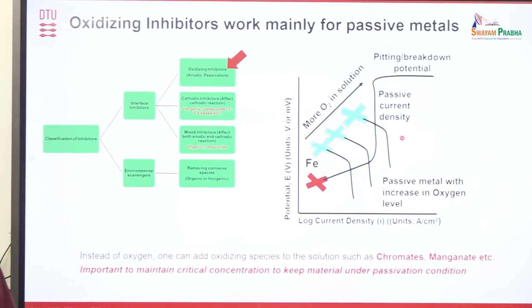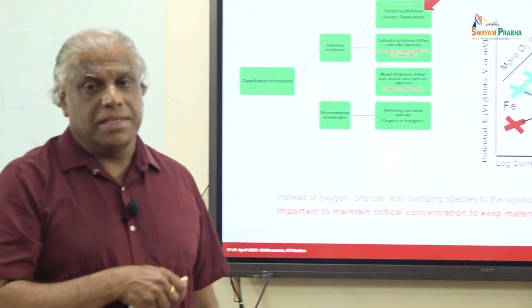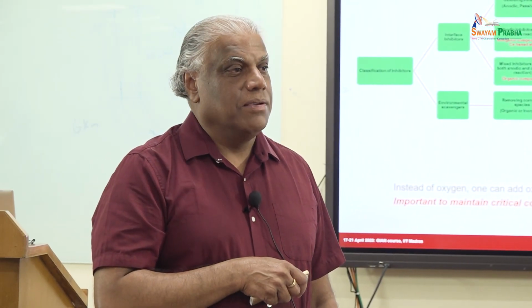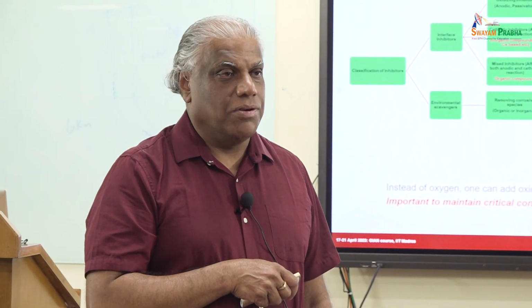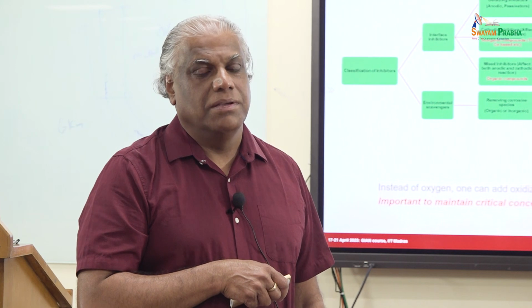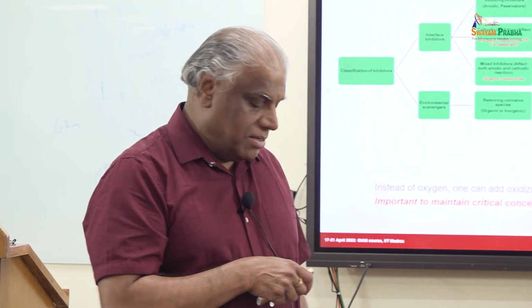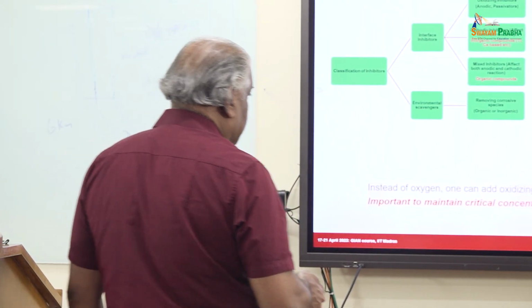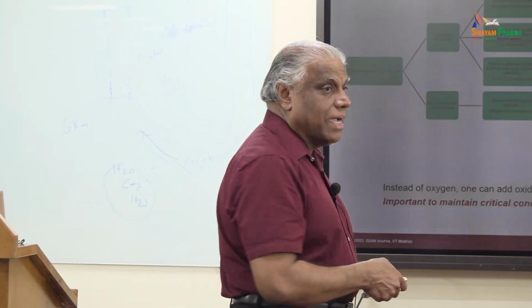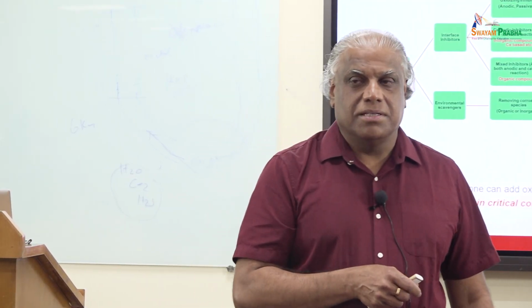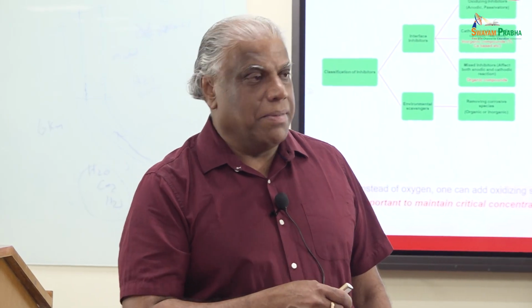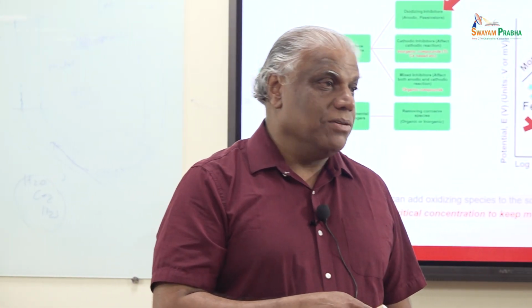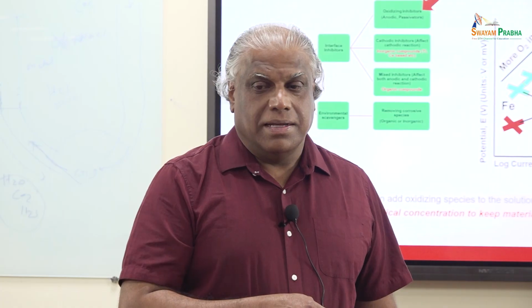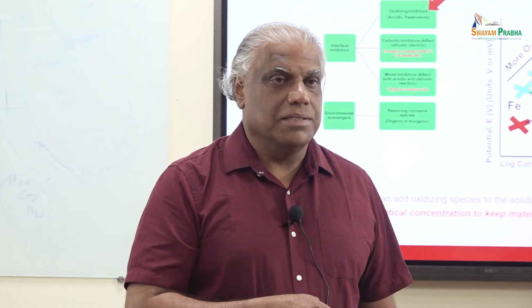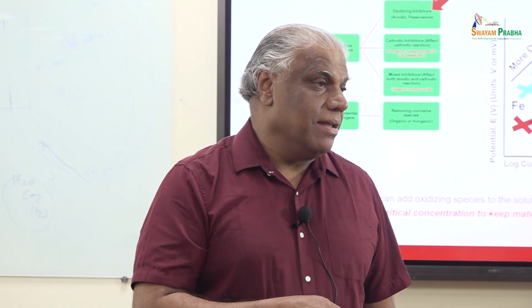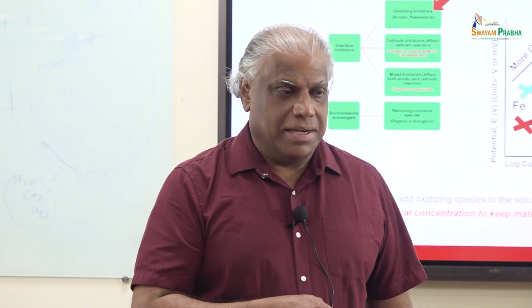And this is what people were using as well. But the only thing is that chromium is banned today because of its carcinogenic effect, and chromium is no longer allowed for these kinds of applications. People are moving to manganate systems, for example. It's not that manganate is a very good system compared to chromium. Manganese is also a heavy element. It also causes problems. So manganese is also not good, but it is better than chromium in many applications.